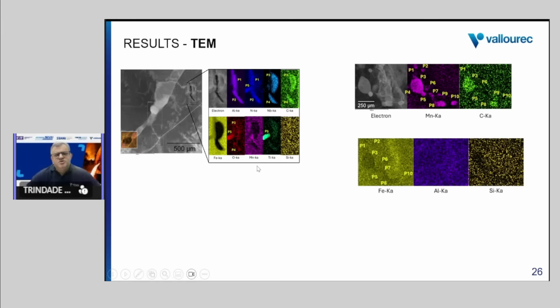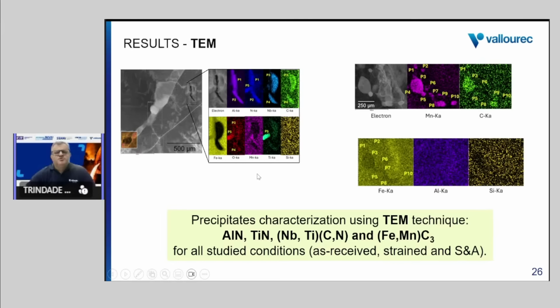And in this transmission electron microscope, what we could observe also is that, independent of the condition, as received, as strained, and strain aged, the precipitates observed are basically the same. There is no change across these three conditions.